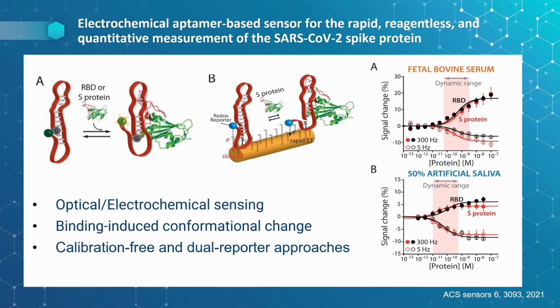So moving toward much more sensitive detection approaches, we also reported an electrochemical aptamer-based sensor for the rapid and reagentless quantitative measurement of SARS-CoV-2 spike protein. For this, we used gold nanowires that were modified with an aptamer carrying methylene blue as a redox reporter. You know that the aptamer in this case was specific to the RBD of the S protein we wanted to detect, and the conformation of the sensor was changing.